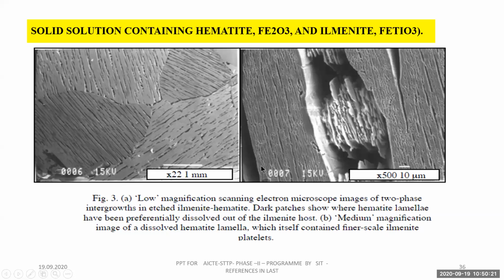If you make it medium, for example, low is 22 times magnification at 1 mm, whereas medium is 500 times magnification at 10 micrometers. So the same black lines are magnified higher. In the black hematite there is also, see, the dissolved hematite lamina which itself contains fewer ilmenite plates. So even though the hematite is consumed by the ilmenite, even though there is a little bit of ilmenite present, we are able to see it by magnification.